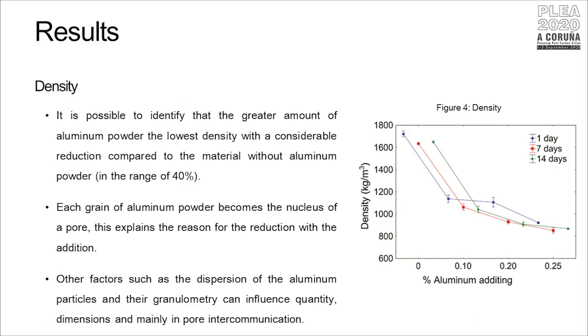In this topic, it is possible to identify that the greater the amount of aluminum powder, the lower the density, having a considerable reduction compared to the material without aluminum powder, in the range of 40%. Each grain of aluminum powder becomes the nucleus of a pore. This explains the reason for the density reduction with the addition of aluminum powder. However, other factors such as the dispersion of the aluminum particles and their granulometry can influence quantity, dimensions, and mainly pore intercommunication.